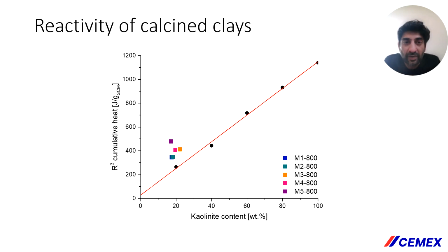In order to further investigate this, the results of the R3 test are compared against a hypothetical trend line. The latter was obtained through testing the reactivity of bespoke SCM blends comprising high purity metakaolin diluted with quartz. Through this, it was possible to evaluate the contribution of 2-to-1 clay minerals present in calcined clays on the overall reactivity beyond what would be expected from kaolinite alone.